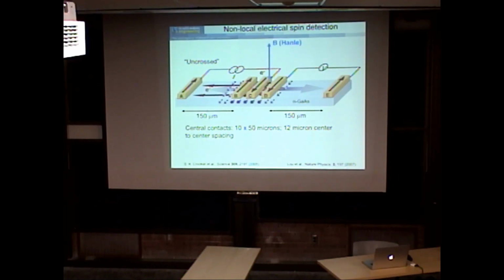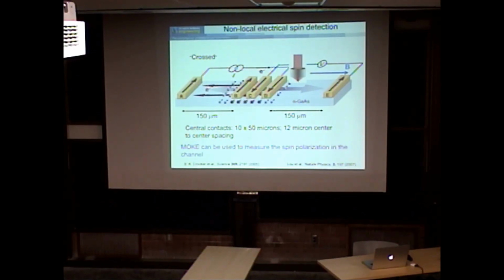If you apply a perpendicular field, you can make these spins precess as you go across from one to the other. So that's a Hanle measurement. That's another way of measuring that you have spin transport. We can also put this voltage probe, with the current going underneath, the contact as well. You can use the magneto-optic Kerr effect. Scott Crooker, for example, did a lot of this, looking at the spin polarized electrons in gallium arsenide to also prove they have spins. And of course, you can change a bias on these contacts.